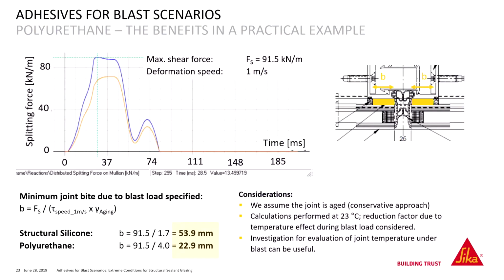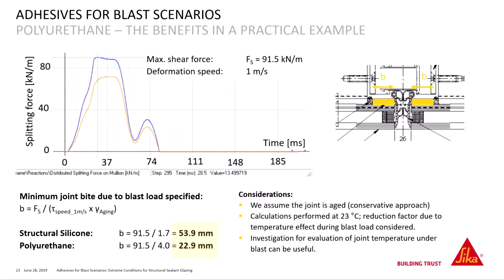Let's come to a practical example. We got some values and parameters from a customer with a maximum shear force of 91.5 kilonewton per meter at the highest peak. When we calculate the joint bite, applying the tau at 1 meter per second, we come to a joint bite with silicone of almost 54 millimeter and with polyurethane of 23 millimeter. That's a significant difference.